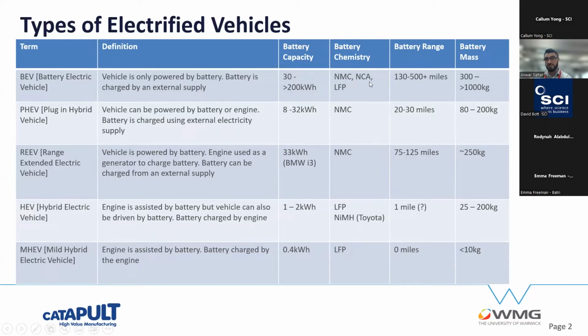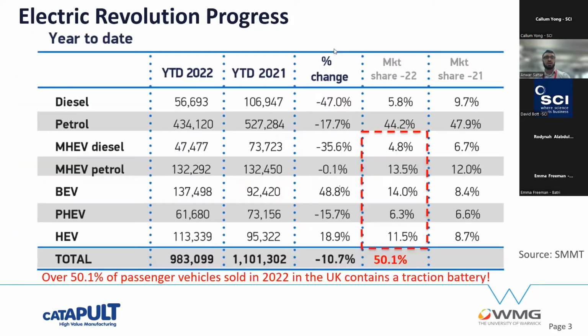To this NMC and NCA, which is the nickel manganese cobalt and the nickel cobalt aluminium, and these have quite a high value. Now, they can be anything from less than 10 kgs to over 1,000 kilograms, as in the case of some of the newer battery packs that are coming out in America. I think the biggest one is something like 1,300 kgs that I've seen so far, and that's in the new EV Hummer, if you want to have a look at it.